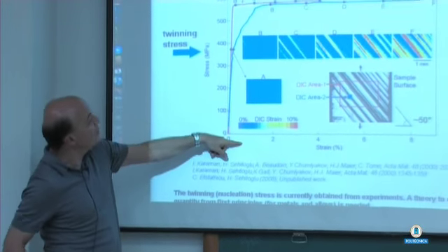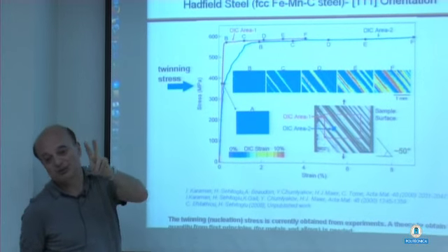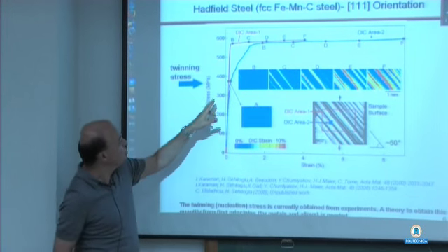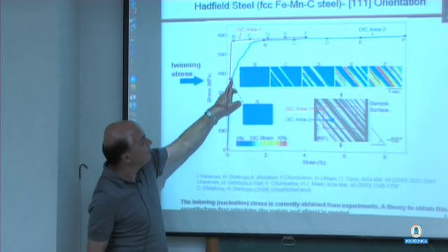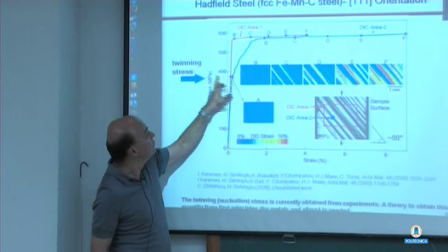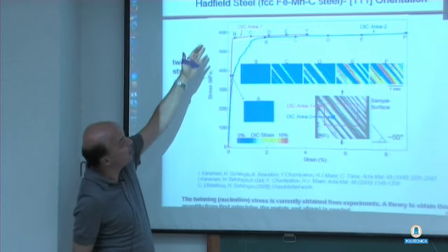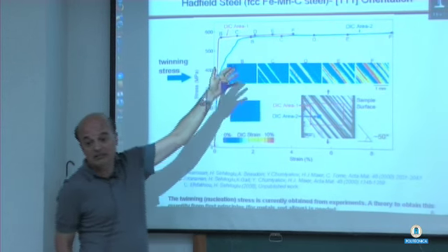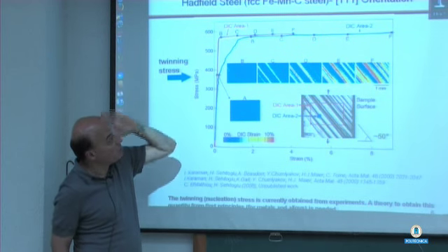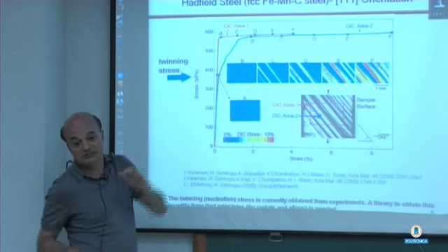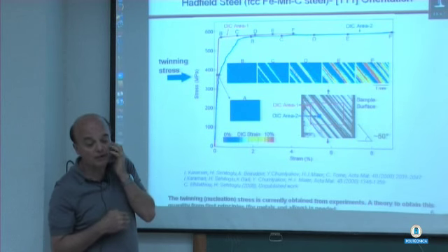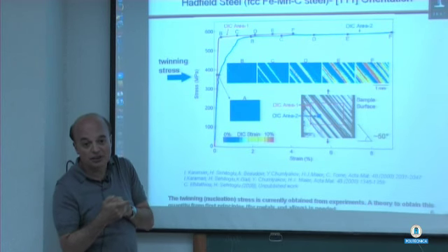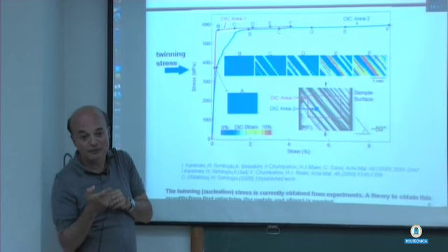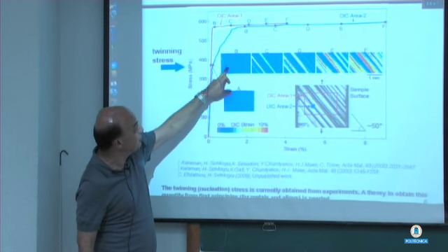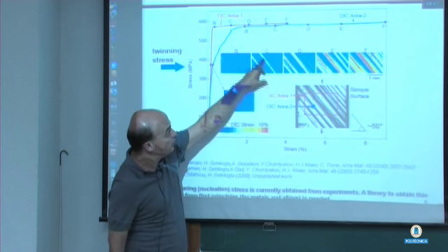So this is stress, this is strain. There are two purposes to this slide. One is to show you that experimentally we can determine the twinning stress. You have to make the alloy. This is an iron, manganese, carbon alloy. This is the Hadfield steel. It's oriented in a certain way. It's a single crystal oriented in the 1-1-1 orientation, pulled in tension. In that orientation, twinning is favorable. You get onset of twinning here, and then more twin bands, and then the twins grow.